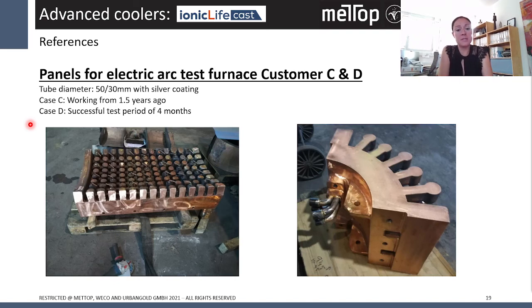What's also very important is different sidewall coolings, especially at highly stressed areas. You can see here a high intensity cooler, a so-called CFM cooler, which drags out so much heat that you create a frozen layer on top of the cooler. You can see this part is going to be cast with some refractory castable. And because of the high heat removal in the furnace, you create a layer of frozen slag or frozen melt, which gives more or less infinite lifetime, even in hotspots.